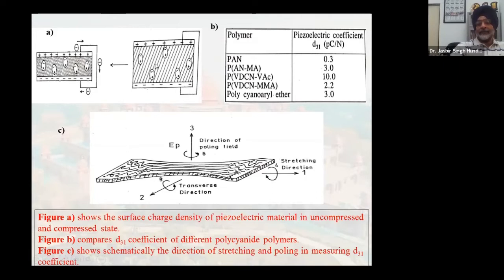So this is the state of a polymer, which of course does have oriented dipoles in it. Dipoles are oriented, but since it is in the uncompressed state, we have only some charges near the surfaces. But when they are compressed, dipoles get nearer to the surface. More dipoles come closer to the outer faces, thereby changing the polarization and giving rise to opposite charges. Thereby, a piezoelectric current starts flowing in a circuit, if it is closed.